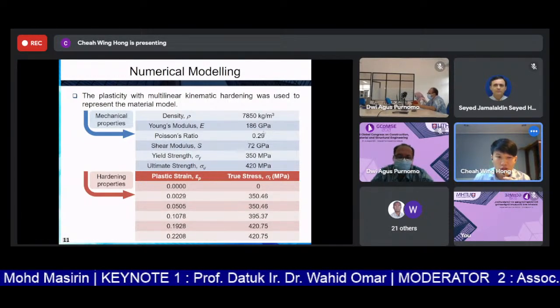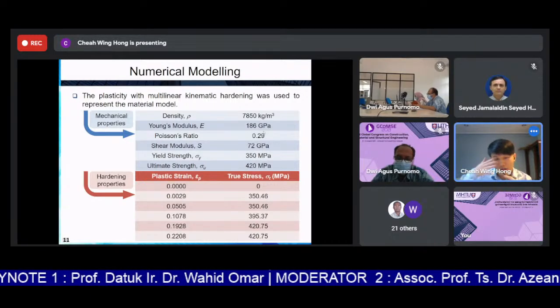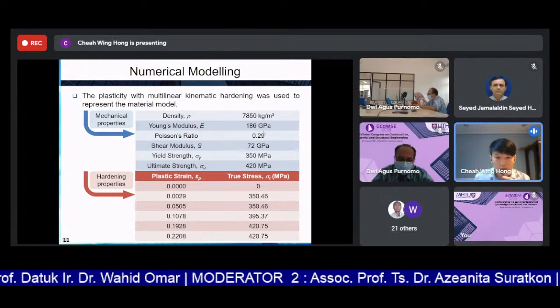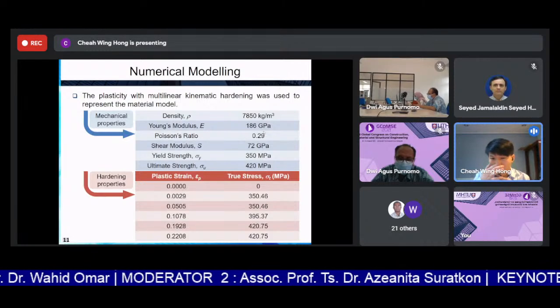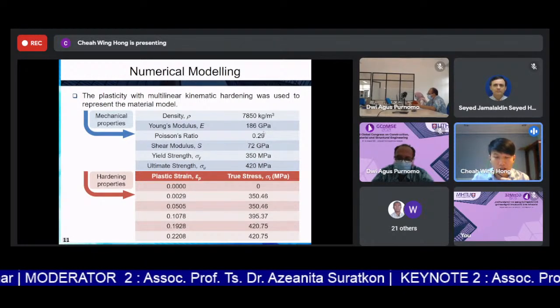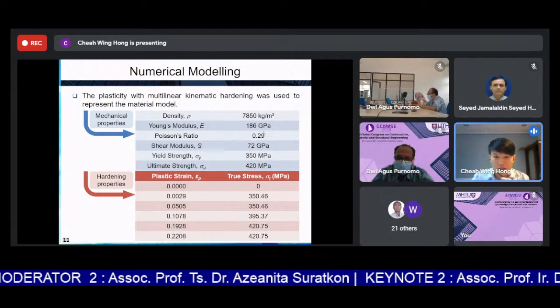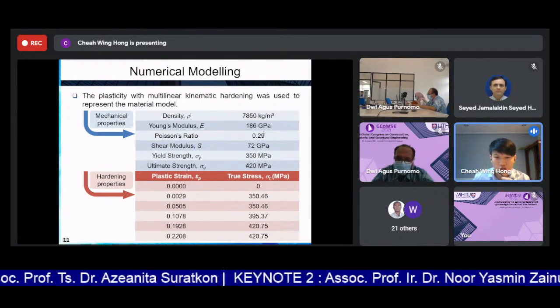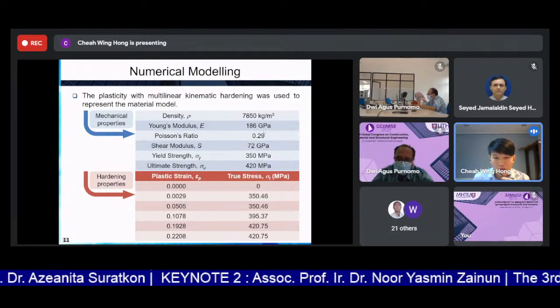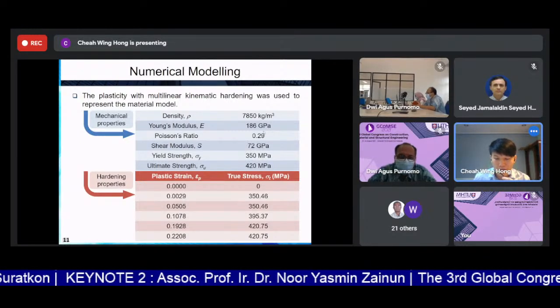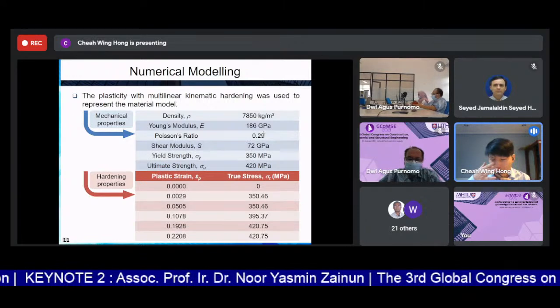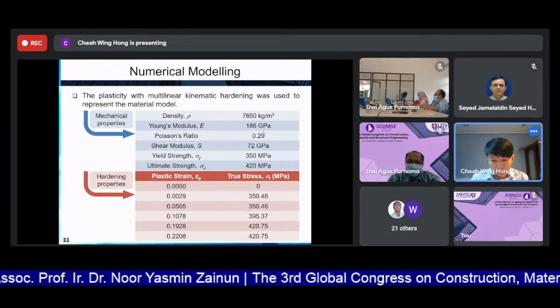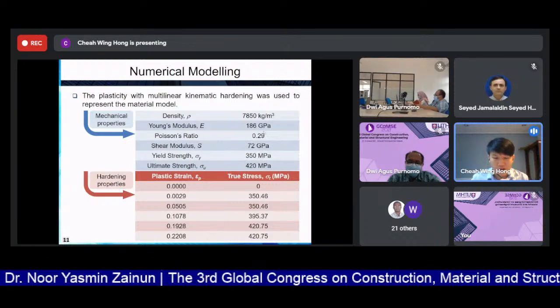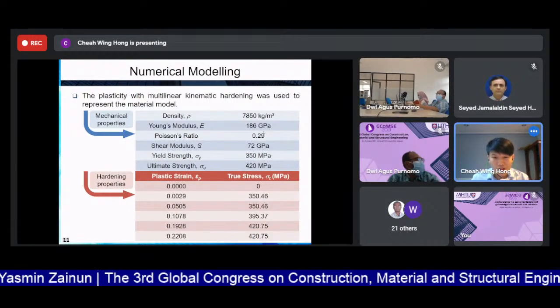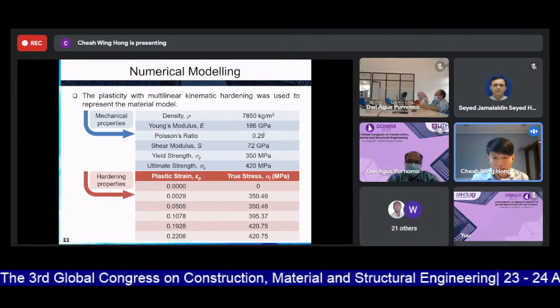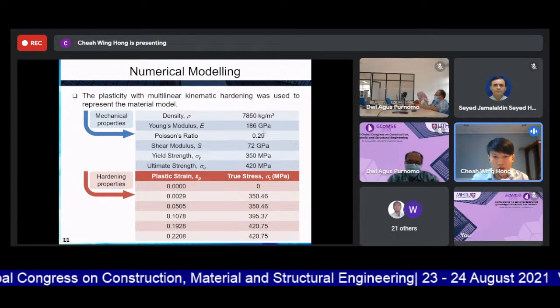For the mechanical properties, the density, Young modulus, Poisson ratio, shear modulus, yield strength, and ultimate strength are based on the previous experimental study. For the hardening properties, the plastic strain and the true stress are also obtained from the previous experimental study. This is because during this pandemic, we were unable to conduct the tensile test for the cold-form steel. So we are using the previous experimental study data that could represent the cold-form steel behavior.